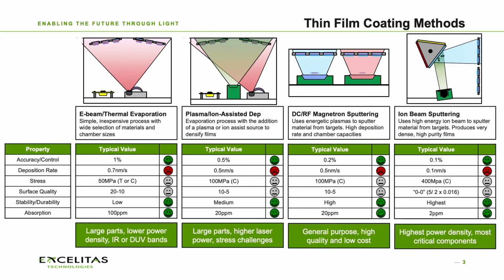The next process on the list here is a magnetron sputtering process. This is sort of a progression from the standpoint of film quality. This is going to be kind of the next step beyond the ion-assisted deposition. In this case, now we're using energetic plasmas to sputter off the material and deposit onto the substrates. It's typically in fairly close proximity to the substrates, although there are methodologies for having it be farther away. And the proximity to the substrates can cause challenges in terms of maintaining high surface quality. So we don't always get the ultimate in terms of surface quality, but we do get decent absorption. The rates are good. It's a good general purpose process.